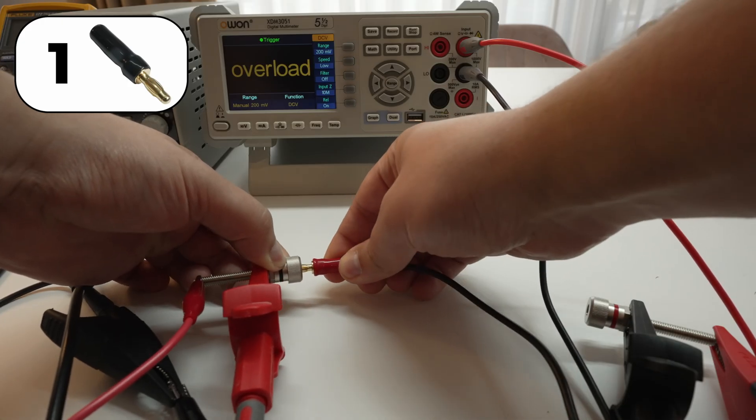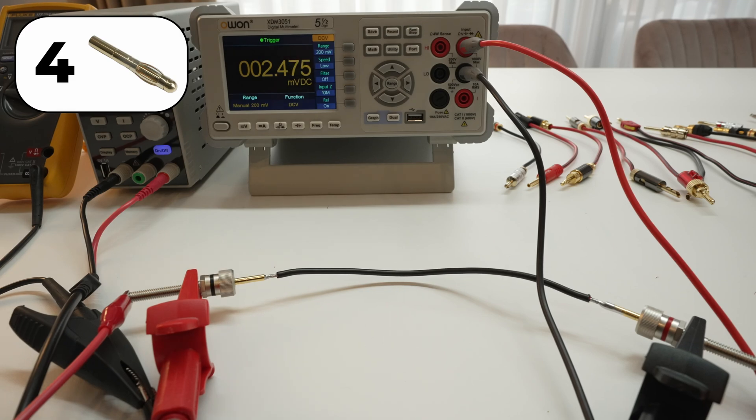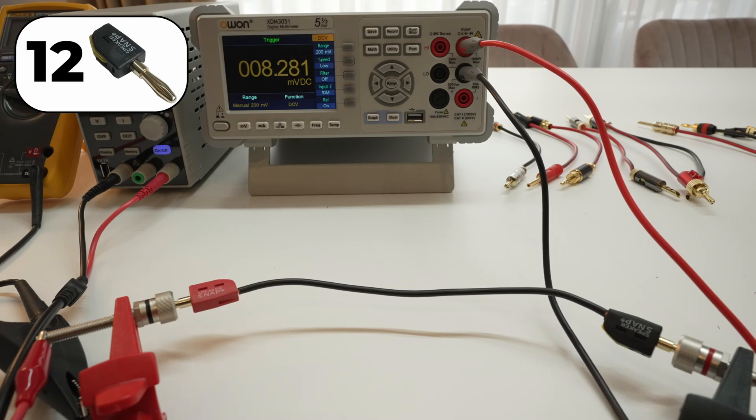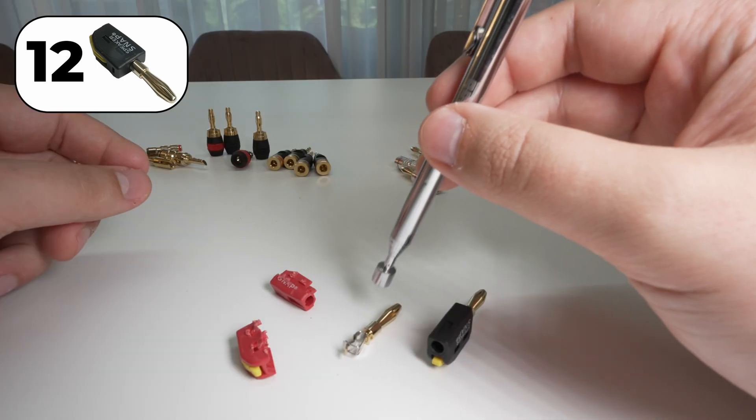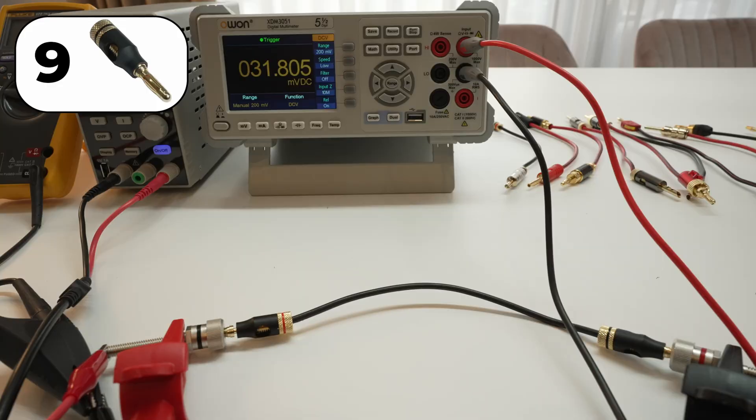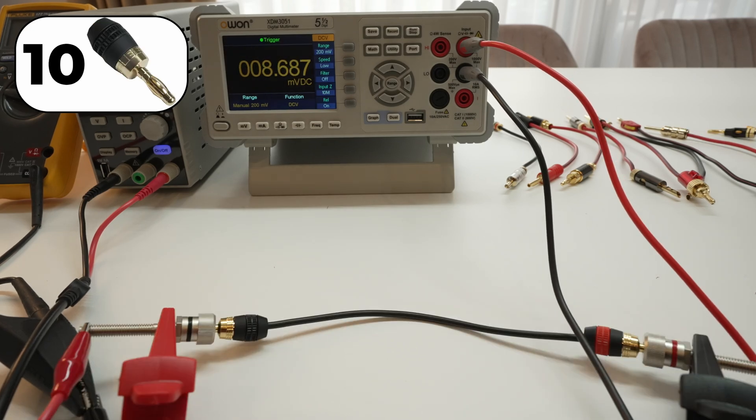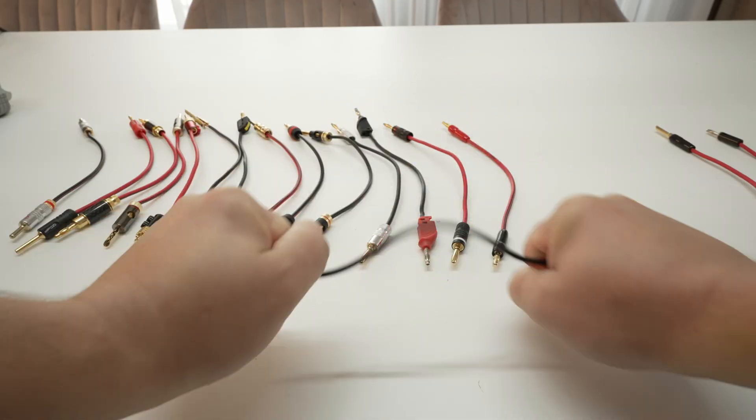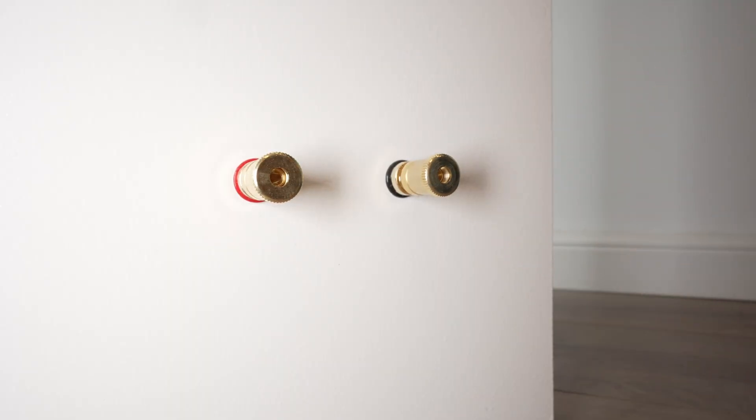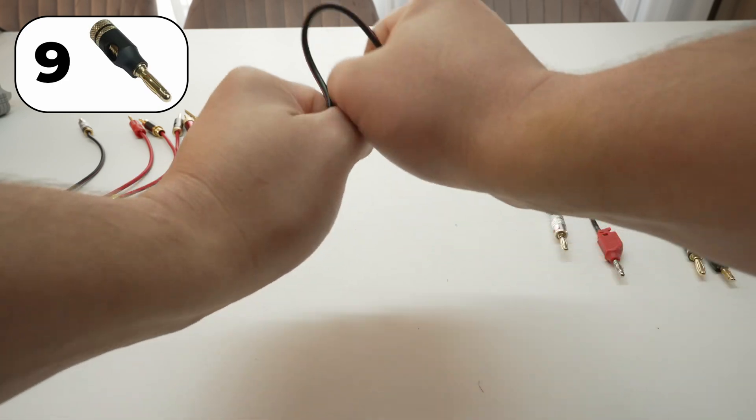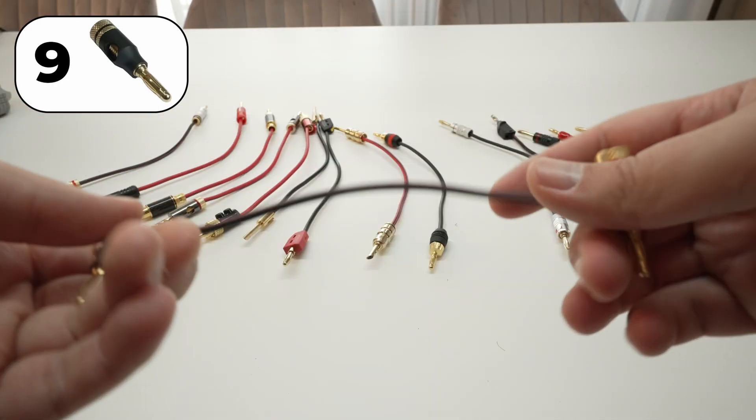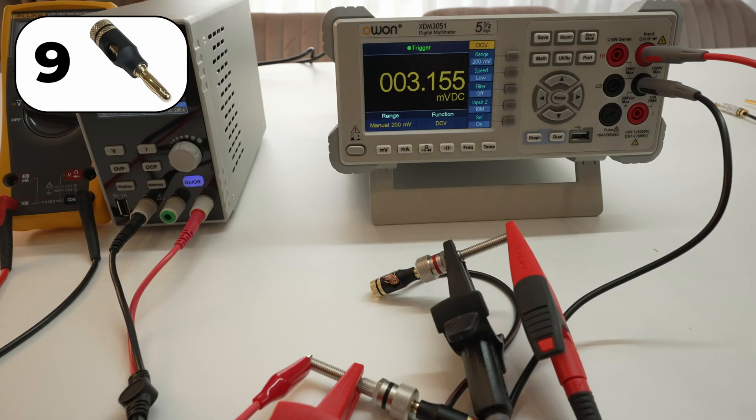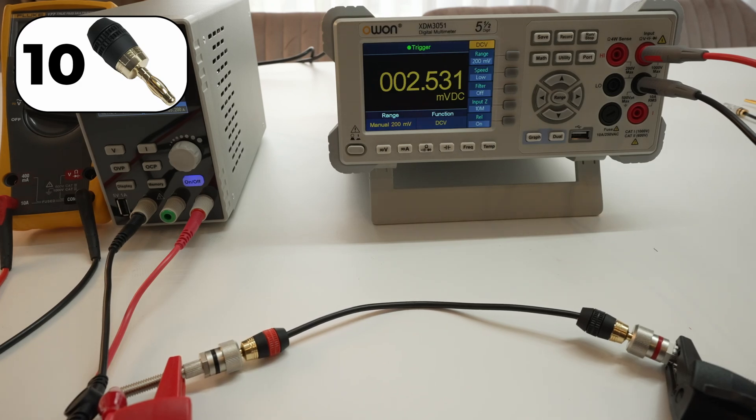The cheapest banana plug failed completely, doesn't even grip to the binding post. The steel banana plug has an expected higher resistance of 10 milliohms. For the rest, measurements varied from 2 and 3 milliohms with some exceptions. Speaker snap banana plugs measured 8 milliohms since it has some steel parts inside - maybe that is the reason. Also some binding posts that are tightened by hand got some suspiciously high numbers like this model with 31 milliohms and this one with 8 milliohms. Now before I draw any conclusions I did a yank test because you'll probably yank on the cable which is hard to reach, and the cheap one failed and also the one with the high 31 milliohms resistance. I tried putting the cable on the other side and now it scored normally and also passed the yank test. The number 10 I tightened it a bit and then it scored normal, so some banana plugs need special attention, otherwise you might be using a subpar quality cable and not even knowing it.